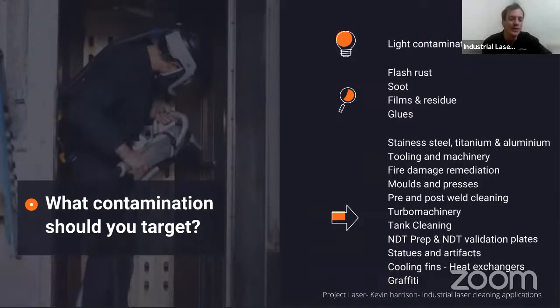That's better. What contamination should you target? Light contamination layers, which can be found as flash rust, soot, films and residues, and glues. Down on the right, we have a bunch of real life applications. As I said before, stainless steel, titanium, aluminium are very easy to clean with a laser because they have light levels of oxides. Fire damage remediation is a target market I think everybody with a laser should look into, because you're basically just removing soot off walls, doors, painted surfaces, chandeliers, whatever you like, really. Molds and presses, very light levels of residue, and 4Jet are fantastic at cleaning those. Turbo machinery and tank cleaning: if you've got a top hat laser, these are great applications with a very positive return.